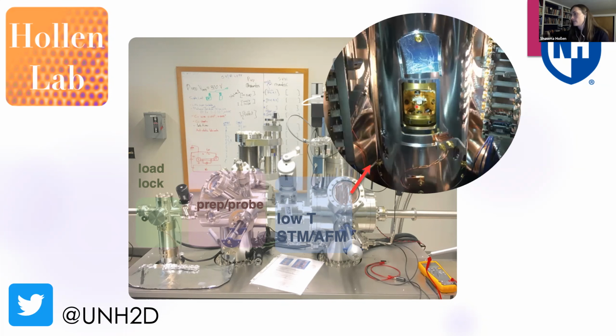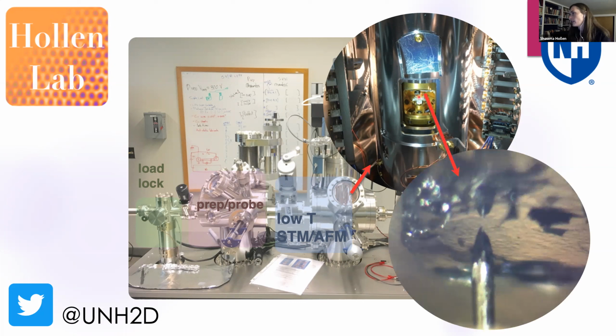Inside this chamber is where the STM lives. These metal cans are really just for the cryogens, because our STM in here is kept at 10 Kelvin. So we need these shields to help keep it cold. But inside of here is where the actual STM is. In our instrument, the wire points up and the sample surface is right above, like this. So you can see here this very sharp wire. This is the surface of graphite. And you can also see the reflection of the tip in the surface.